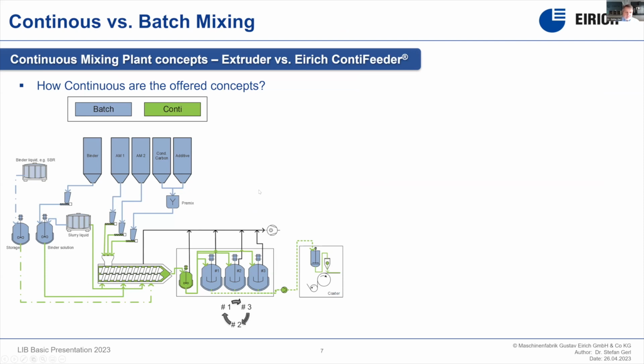And you have lots of equipment like powder dosing, pre-mixing, binder solution preparation, and of course also the degassing and storage tanks between the mixer and the coater as a batch-wise operation. This also has to do with the fact that no operating company in a gigafactory would allow applying directly out of the mixer without qualification and without any buffer tank directly onto the coating line.